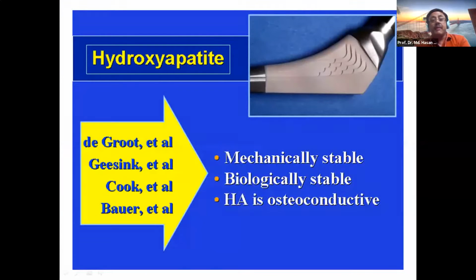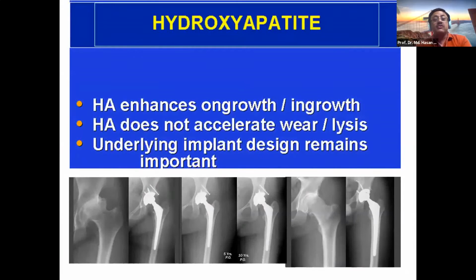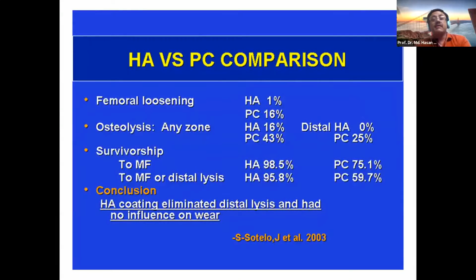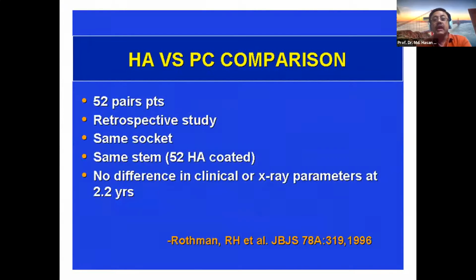So about hydroxyapatite coated, a study showed that it is mechanically stable, it is biologically also stable, and hydroxyapatite is osteoconductive. And hydroxyapatite enhances on-growth and in-growth. Hydroxyapatite does not accelerate wear and lysis, and underlying implant design remains the important thing. So there are some studies which favor that hydroxyapatite is superior to porous coated material, but some studies showed no difference in clinical or X-ray parameters in comparison of hydroxyapatite and porous coating implants.